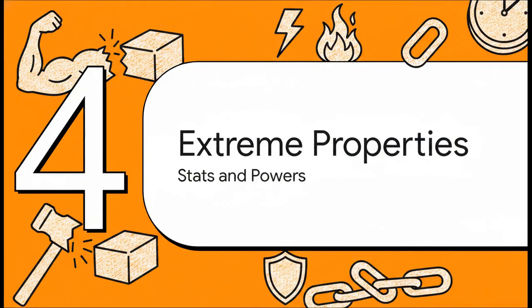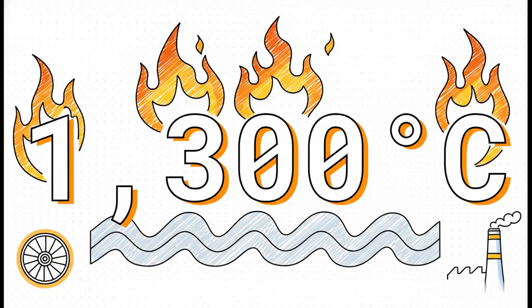Section 4. Extreme properties and powers. Let's look at the stats. 1300 degrees Celsius. Just to put that into perspective for you, unless you're making a habit of hanging out inside an active volcano, that is unfathomably hot. But because zirconia has incredibly low thermal conductivity, meaning it is a fantastic insulator, fully stabilized zirconia can comfortably operate as a thermal barrier coating. They literally spray this stuff directly onto the metal turbine blades inside roaring jet engines and gas power plants. It protects the structural metals underneath from temperatures that would absolutely melt them into a liquid puddle.